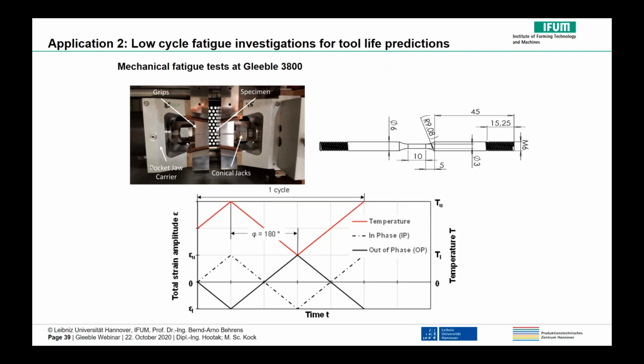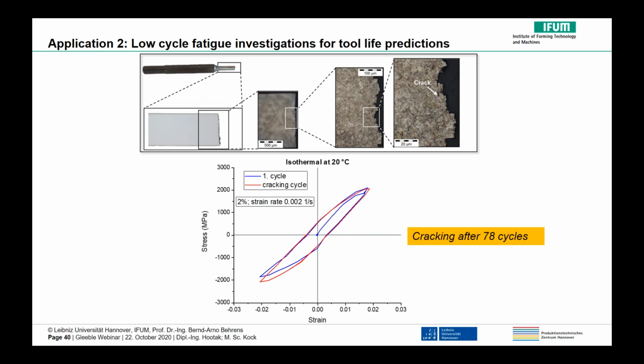Crack initiation can be detected by the change of the stress amplitude and its sudden drop. In this work, the crack criterion was fulfilled when the value decreased by a minimum of 50%. The following figures show the fracture regions of the specimens after the different types of thermomechanical fatigue tests. Micrographs were taken by means of grinding longitudinal sections. Therefore, pieces from the failure areas were taken from the specimens by wire erosion, which were subsequently etched to make the microstructure visible.